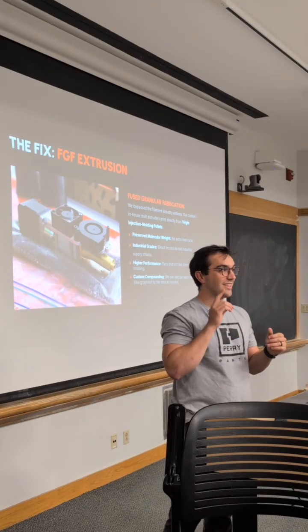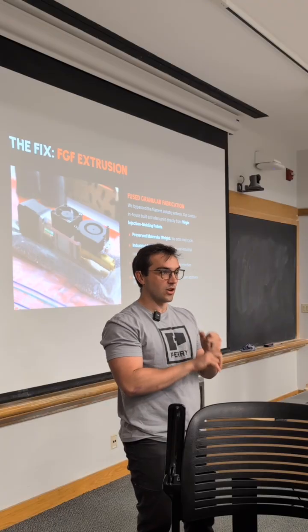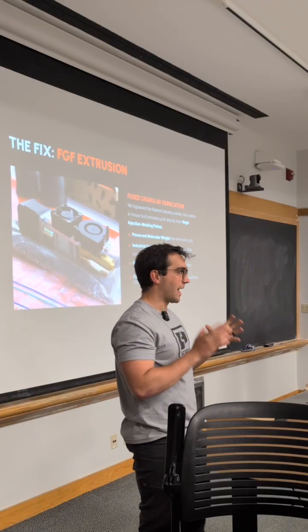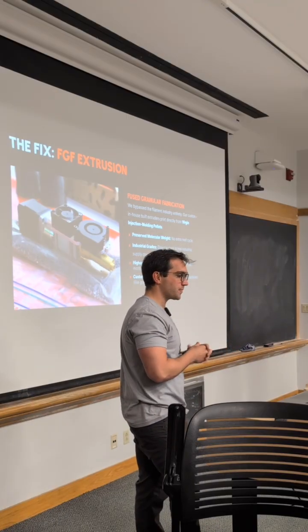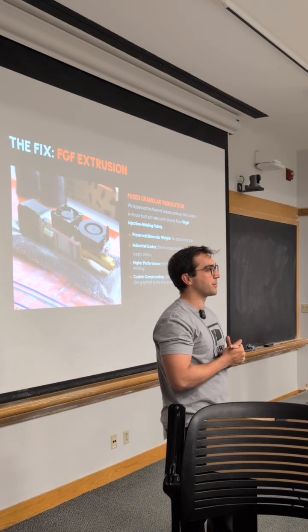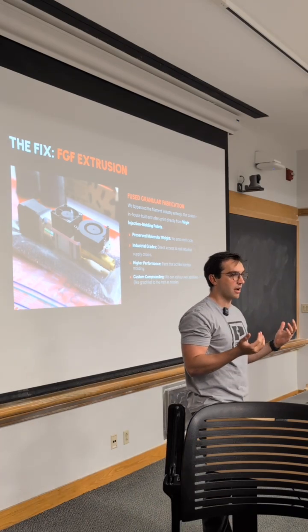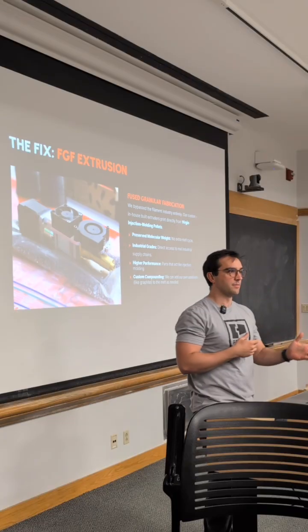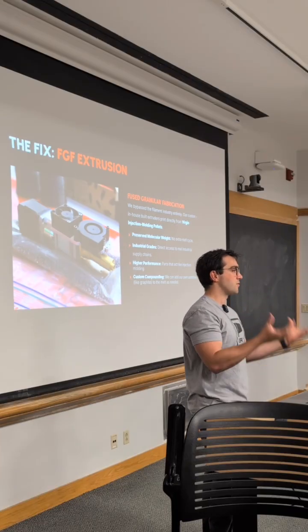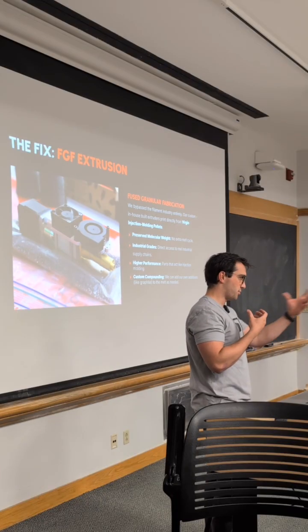One, we can use the exact same polymers that you would otherwise injection mold or extrude without having to melt them into filament. And it opens up all those opportunities for custom compounding that we talked about prior. So you can do graphite, you can do molybdenum, you can do whatever you want, as long as you can coat the pellets in it and then put it into the print head.